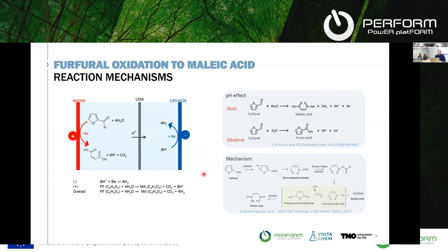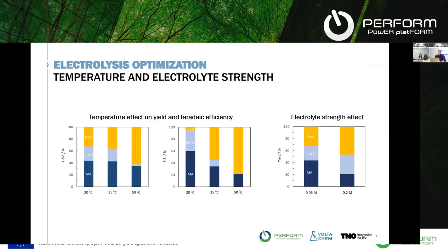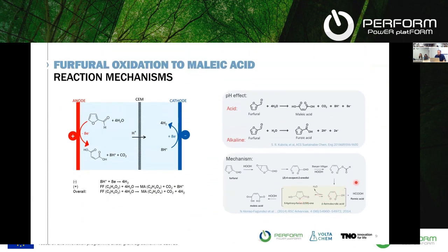And then we went on to carry out a bit of mechanism investigation, because when we carry out this oxidation reaction from furfural, we see something different than maleic acid. Or let me rephrase that: together with maleic acid, we see some other intermediates. And specifically, we see 5-hydroxyfuranone being produced as well. So for us it was important to figure out whether this proposed mechanism is what is actually happening in our reaction. We did a bunch of different tests to figure out whether this 5-hydroxyfuranone can also be oxidized electrochemically on lead oxide to go to maleic acid. And indeed, we find that if we start exclusively from 5-hydroxyfuranone, then we can actually convert that to maleic acid.